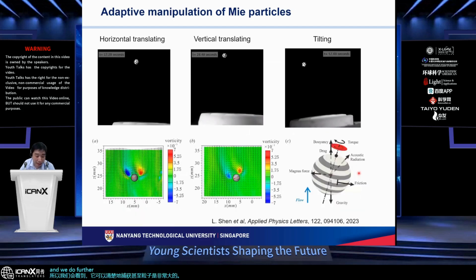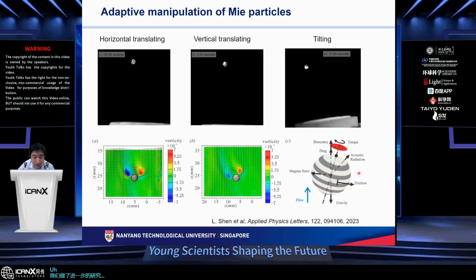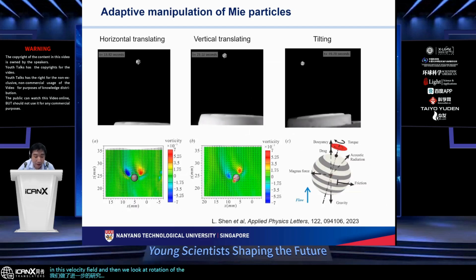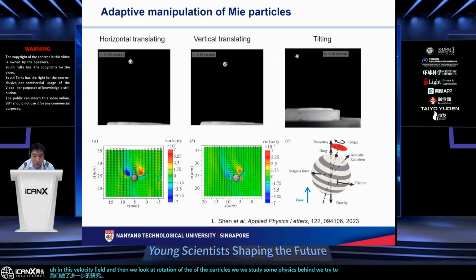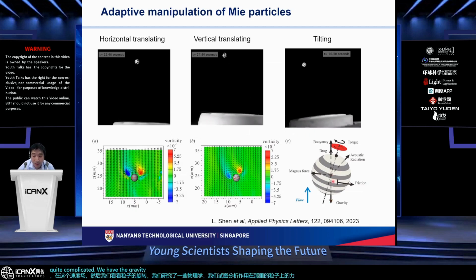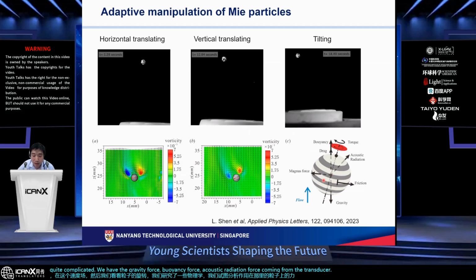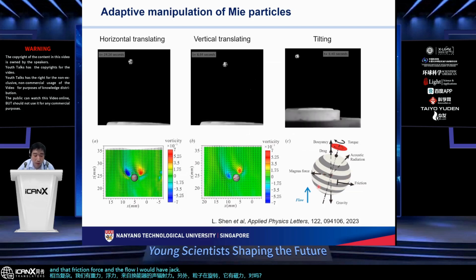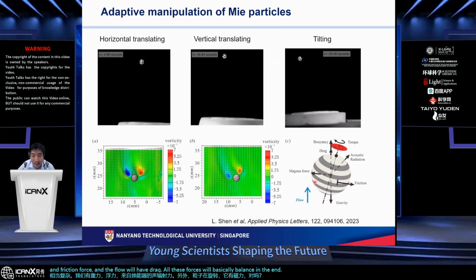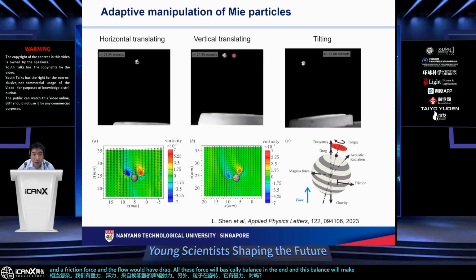We did further studies of the velocity field, and we looked at the rotation of the particles. We studied some of the physics behind it. We tried to analyze the forces acting on the particles. It's quite complicated. We have the gravity force, buoyancy force, and the acoustic radiation force coming from the transducer. Also, the particle is spinning, so it has a magnus force, a friction force, and the flow creates drag. All these forces basically balance in the end, and this balance makes the particles self-stabilized.